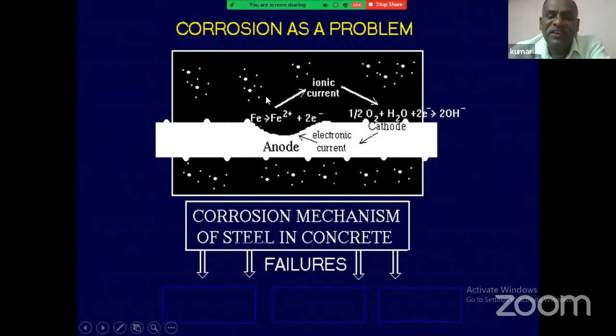That means Fe releases, and correspondingly the electrons are flowing to the cathodic side. It forms OH minus ions. Fe(OH)2 is forming. Then after that, Fe2O3 and so on are forming, which are the further corrosion products.